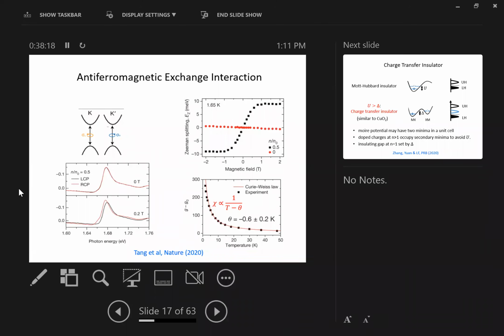If you look at that as a function of applied magnetic field, you find that when you are in the Mott insulating states, the magnetic response at low temperature is greatly enhanced, by a factor of almost 200 compared to the case without any doped charges. And also, this curve is very much similar to the magnetization curve. If you have a system of local moments when you apply a magnetic field, when the magnetic field is larger than some thermal energy scale or larger than the energy scale associated with exchange interaction, then you get fully polarized.